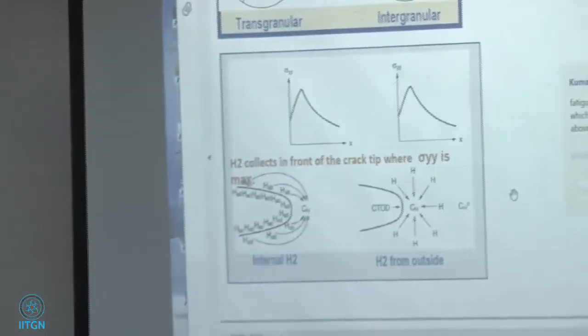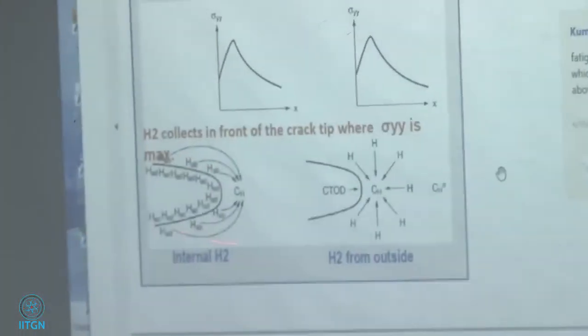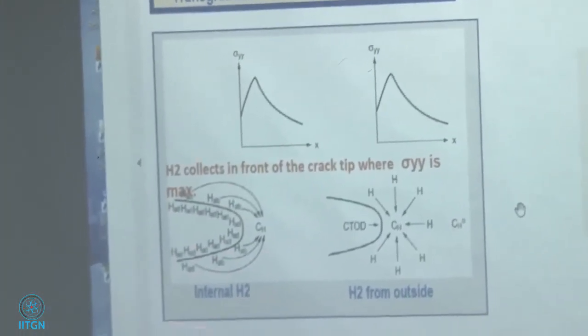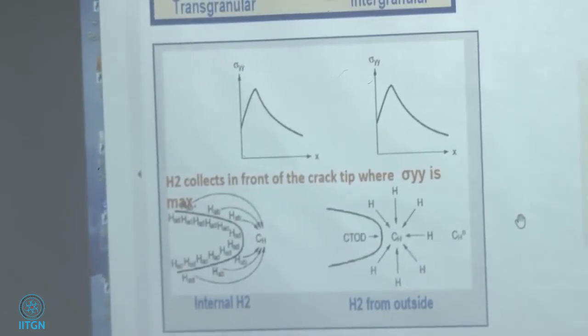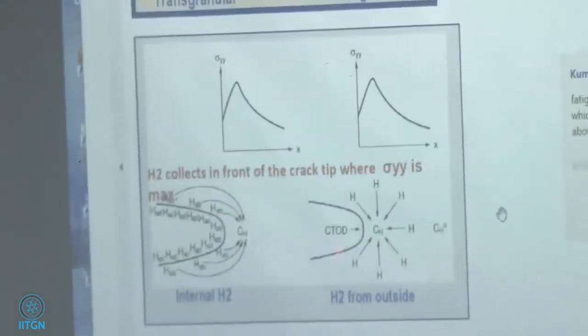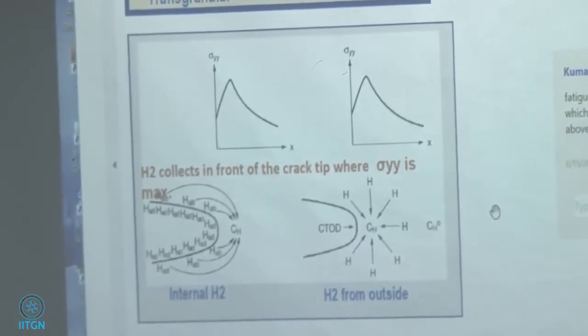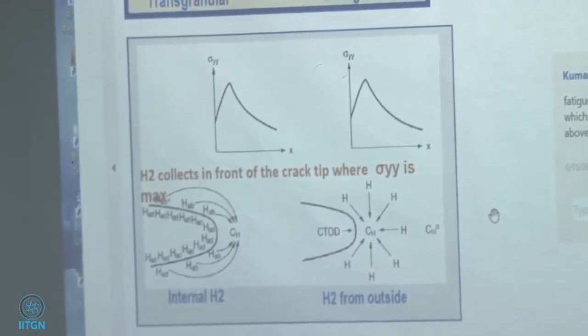So this is something, hydrogen embrittlement. Where is our hydrogen embrittlement? Hydrogen embrittlement, right? So here we are, like a crack, there's a crack. It's just a schematic. I'm just showing you a schematic. There is a notch or a crack, and let's imagine there is some hydrogen, or even coming from outside too, or internal, doesn't matter. See, right in front of the crack tip, all this hydrogen will collect, because of the elastic field. There's always a question that comes up on the exam. Hydrogen is an interstitial atom. Where is it going to go and reside on a dislocation? Because if you put a dislocation,